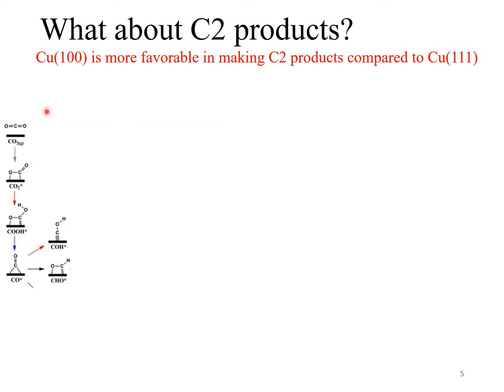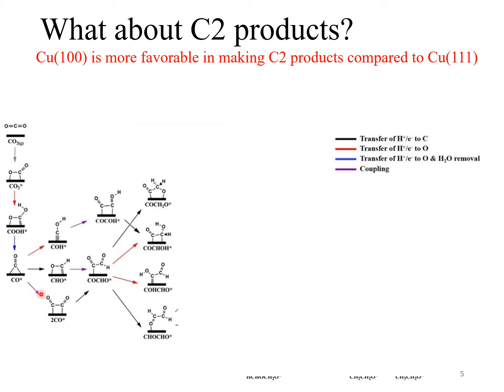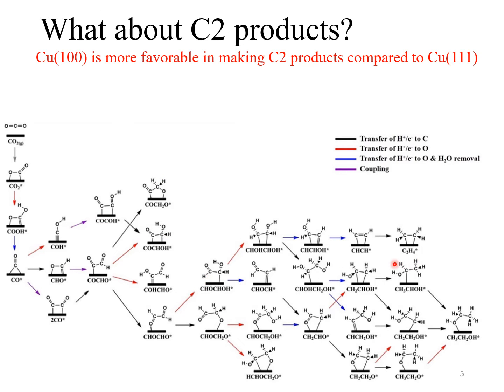Here I'm showing you a schematic of CO2 binding onto the surface, star, and then getting reduced and further reduced to make CO, and this CO could get further reduced here, making COH or CHO on the surface. Another reaction is that CO can react with another CO, or these two COH or CHO can react with CO to make these what we call the C2 reaction intermediates. And after this, the reduction reaction can proceed, and in the end, we can have ethylene or ethanol.